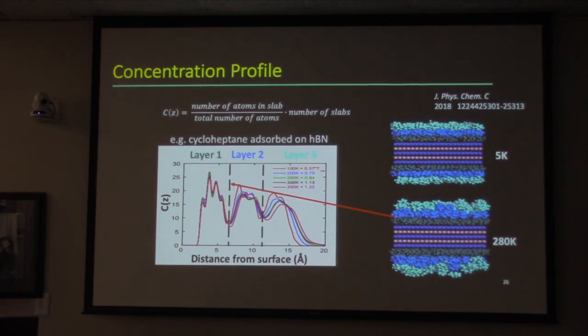There's an increase in the density around those points. It turns out that, depending on the interaction, this is the concentration profile, in this case of cycloheptane on hexagonal boron nitride. We've done these simulations for all of the ones that we've studied, but this one is a good example. It tells you the location perpendicular to the surface of some particular component of the molecule. You follow both the carbons and the hydrogens.